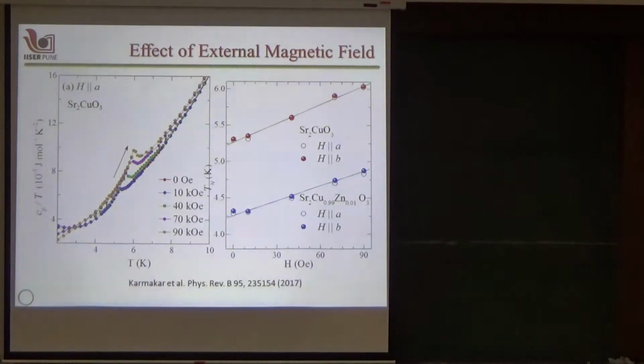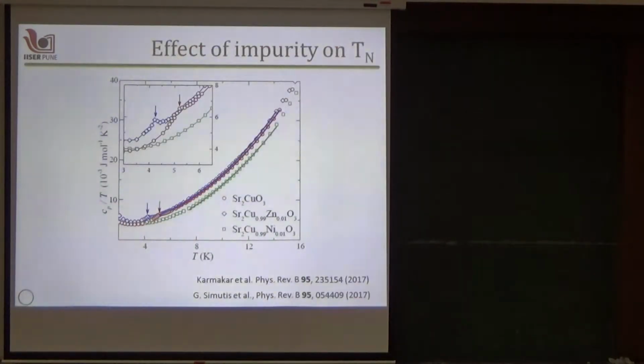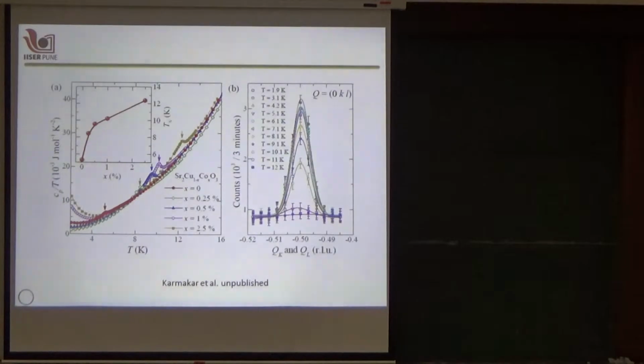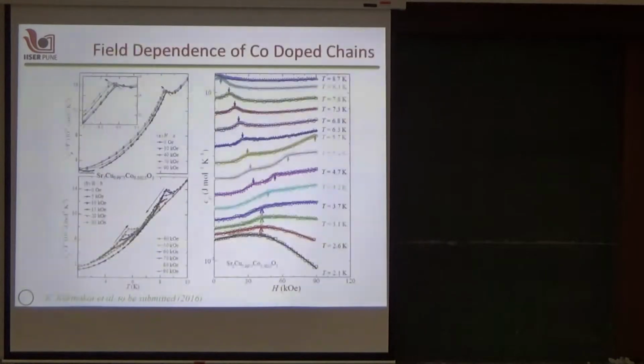Sorry, this is a repeat of the previous slide. So now we put different concentrations of cobalt, and we see that the transition temperature scales with the concentration of cobalt, and this is the elastic neutron scattering peak for 1% of cobalt doped sample at different temperatures, and you see that the magnetic peak appears right below 11 K or so. So that's the proof that it's a bulk transition.